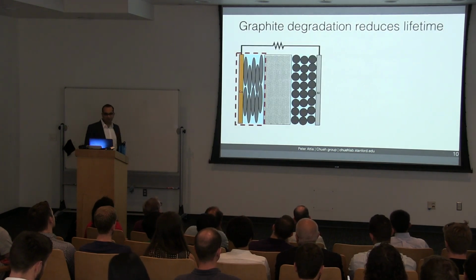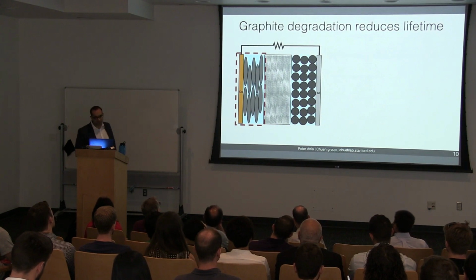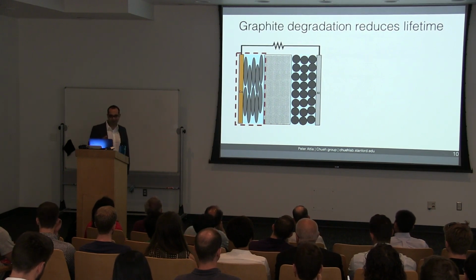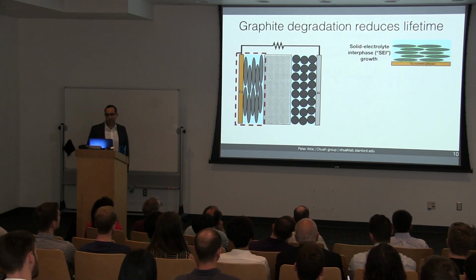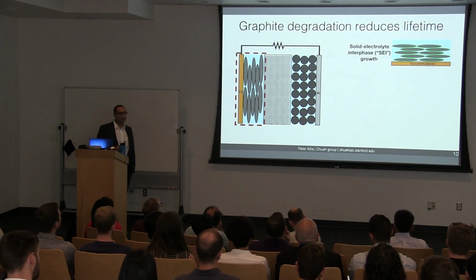is dead. So as it turns out, most battery degradation is on the graphite side, especially during fast charging. Now there are a lot of different battery degradation modes, but I only want to focus on 3 of them here. The first is growth of the solid electrolyte interface, or SEI. It grows on the surface of the graphite particles. It consumes active lithium and reduces the overall capacity of the battery.